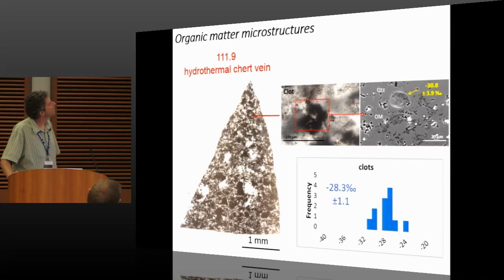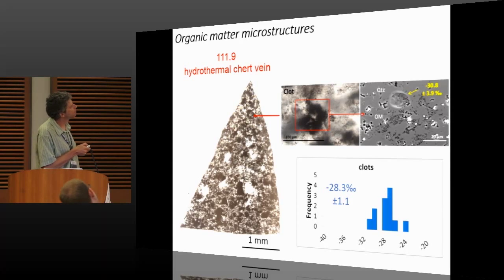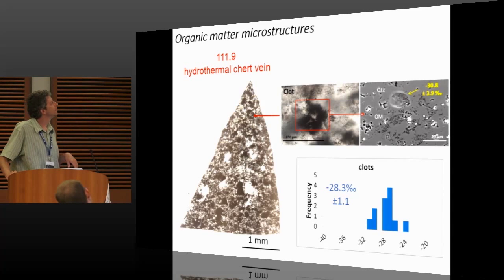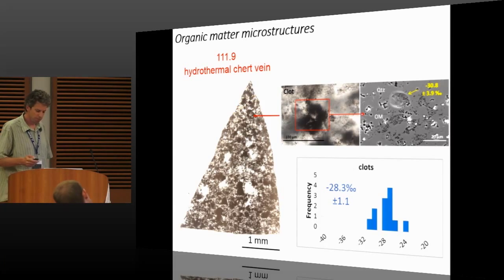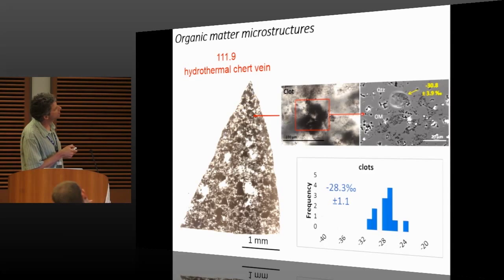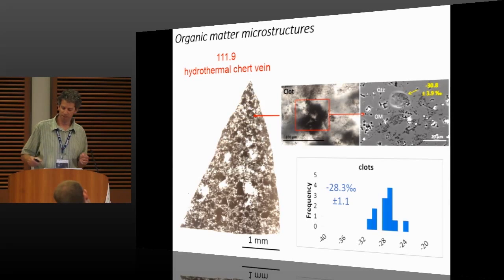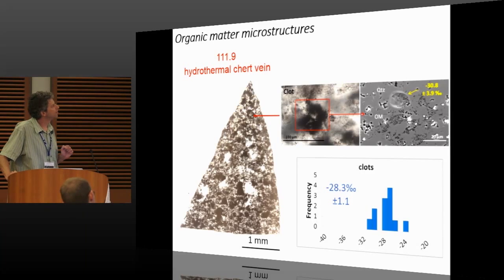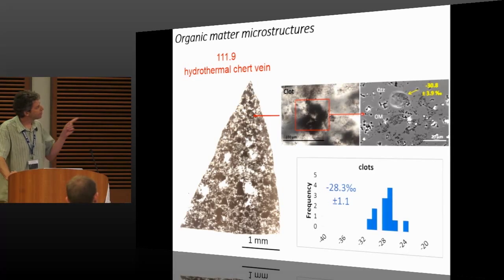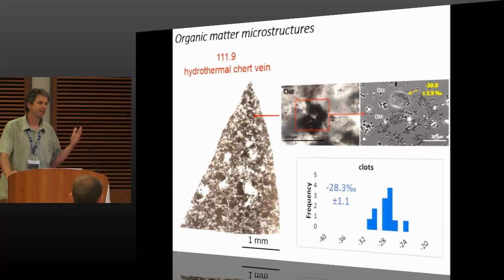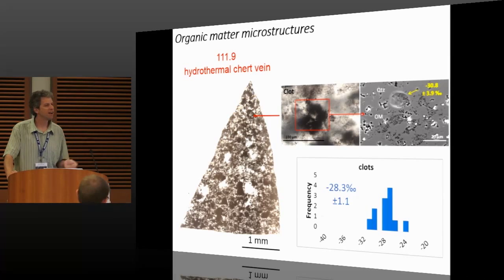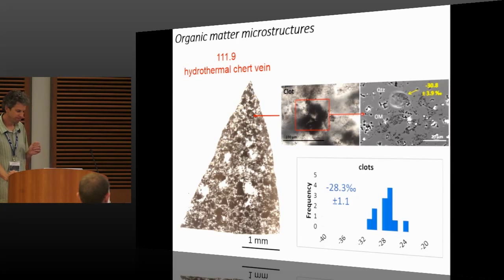Here is the sample from a hydrothermal chert vein. And in this sample, the only organic microstructure that we have identified is these organic matter clots, similar in appearance to the type 1 clots, which I have shown in the bedded chert sample. And isotopic composition in these clots are also similar to the isotopic composition of the type 1 clots in the bedded sample, with an average of about minus 28 per mil. So these textural and isotopic similarities suggest that the clots, both in the bedded chert and in the hydrothermal chert vein, have the same origin.